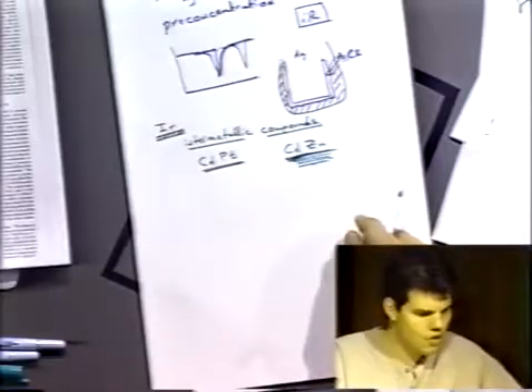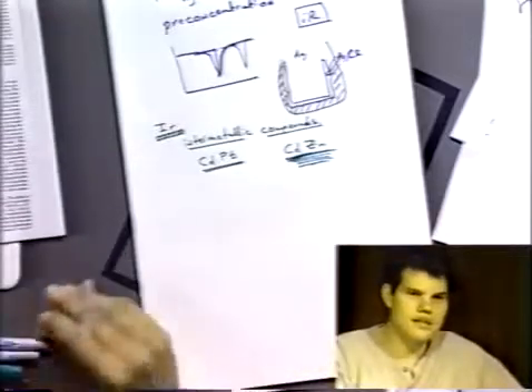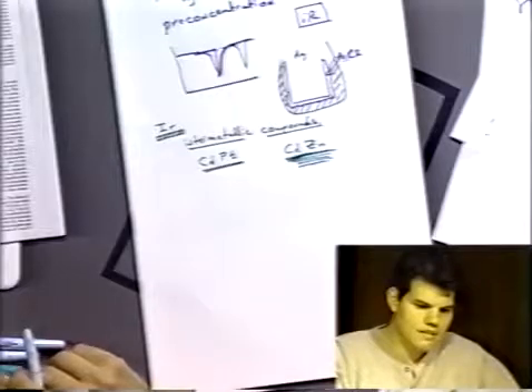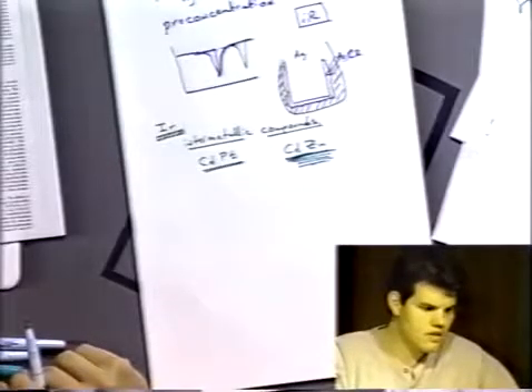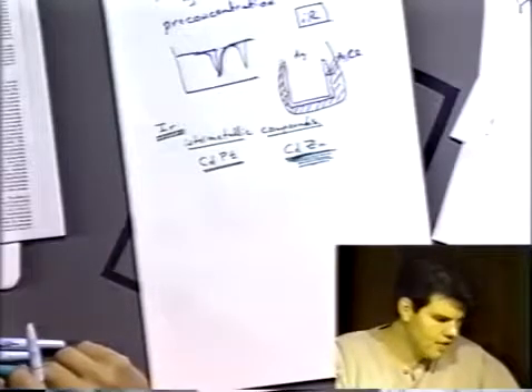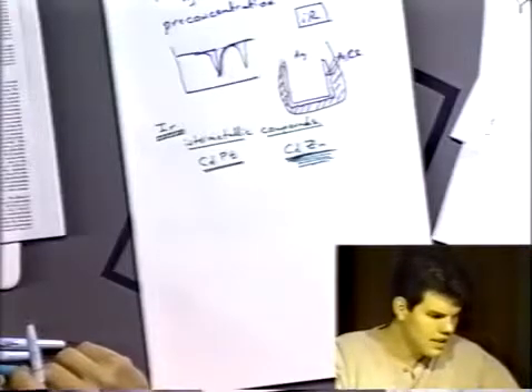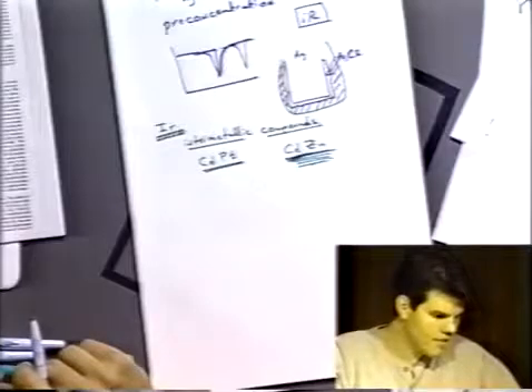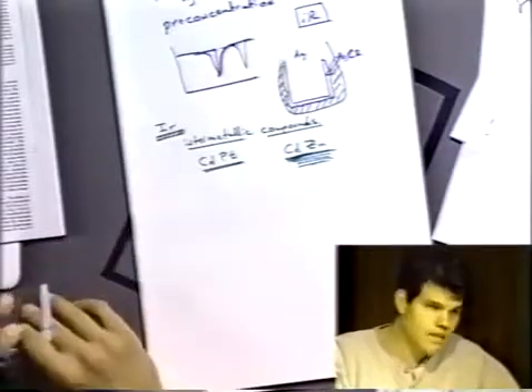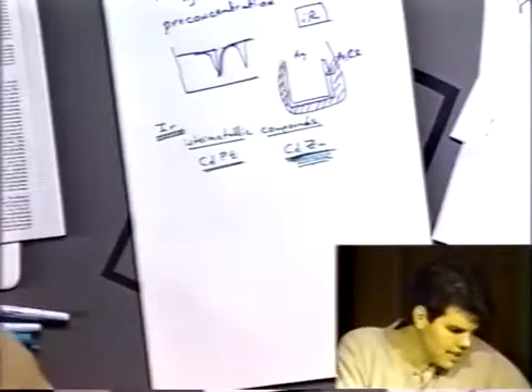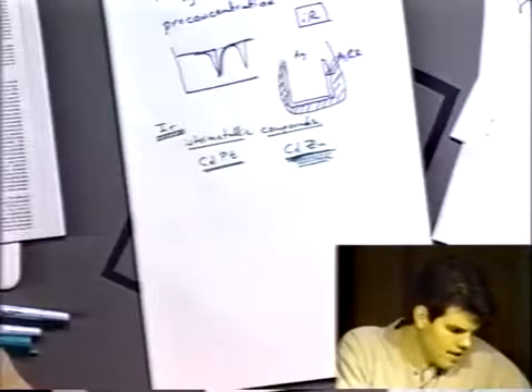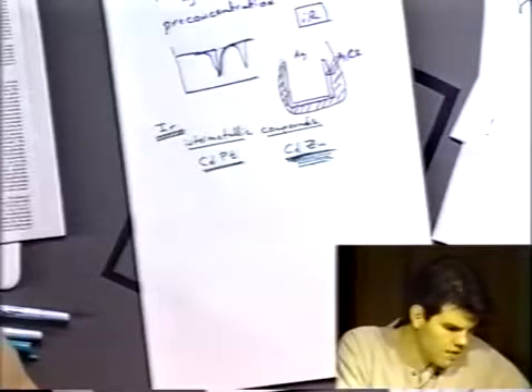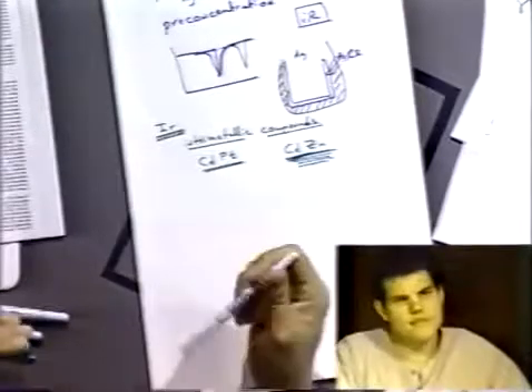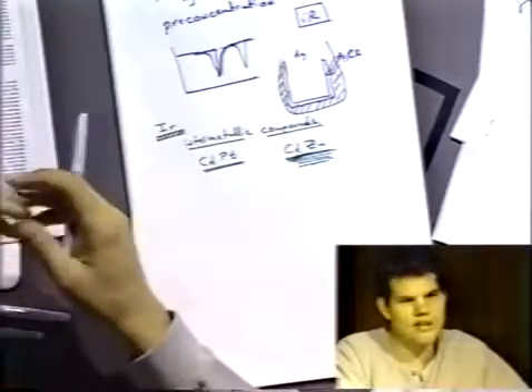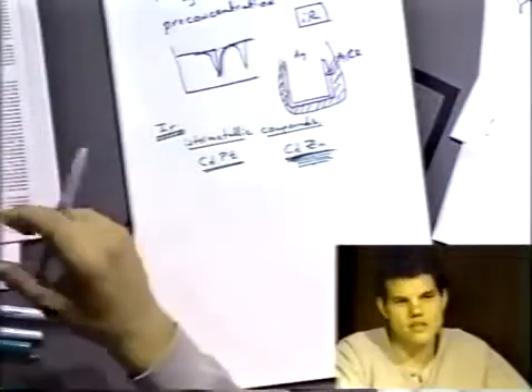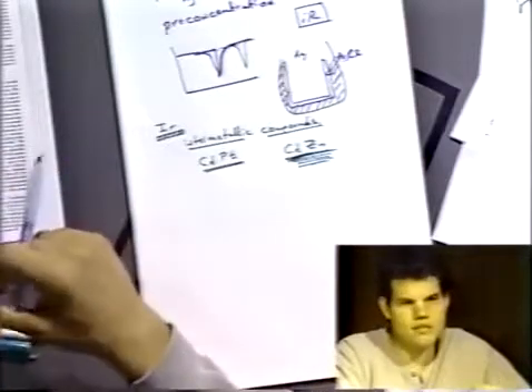The big problem with iridium is it's so difficult to work with. You can't make small wires out of it. It's not ductile. It's also very hard, and it's very chemically resistant as well. So you notice how they made the electrode is kind of interesting. They started with a small wire, pretty small wire, 127 micrometers diameter, but that's not small enough. They want tens of micrometers or smaller. And then they etch the wire by immersing it in a platinum crucible containing a molten salt mixture of sodium nitrate and sodium chloride at 445 degrees centigrade. So that's quite a reactive pot of molten salt, and they have to go to that extreme to get a good etching of the iridium because it's so chemically resistant otherwise.